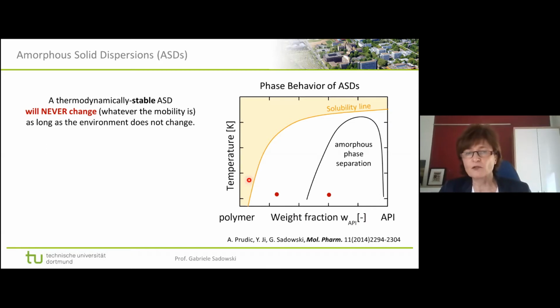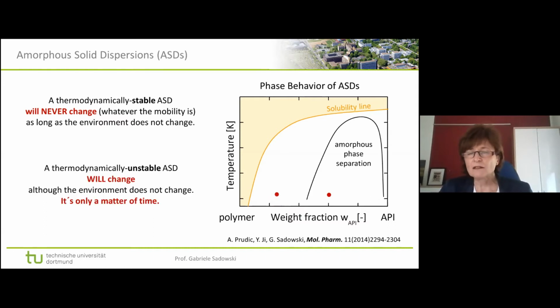So none of them was to be found here, because what you see is that at these low temperatures, you can have only a very little API content in a tablet. And that means you would either have too little API in a tablet, or you would have a huge tablet, more like a cake, for the given API dose. And that means the ASDs are usually supersaturated, meaning the API loading is usually higher than the solubility of the API in the polymer. And that means that there is a certain danger that they will change. It's only a question of how long it takes.